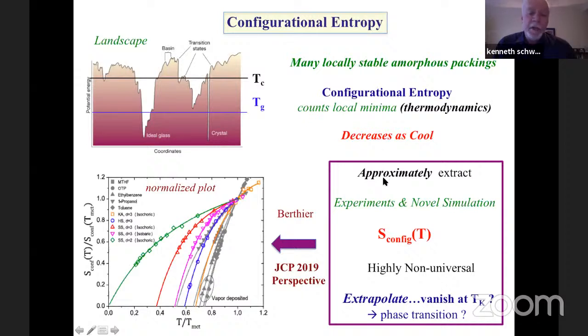So determining the configurational entropy has never been very easy. One can approximately extract it experimentally, and there's been recent novel simulation approaches that have been able to get a handle on it with simulation models. So there's this very nice summary of configurational entropy by Ludovic Berthier and co-workers in a recent JCP perspective that shows the configurational entropy in a normalized way as a function of cooling. Of course, the configurational entropy goes down as you cool, but the way it goes down is very non-universal.